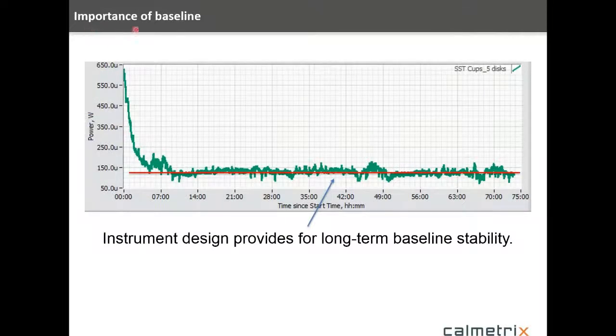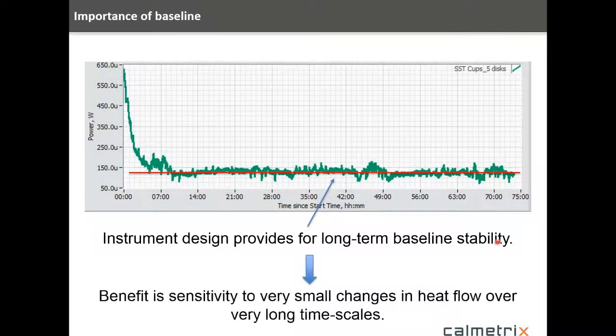Like other analytical instruments, baseline is very important. The isothermal calorimeter is designed for very long-term baseline stability, and that's very important. It basically provides us the sensitivity to look at very small changes in heat flow over very long time scales. So, of course, there's two aspects of sensitivity. The raw baseline noise is one issue, but just as importantly is the long-term baseline stability, because these reactions that we're looking at are very small changes in the baseline, and so a flat baseline is important to have the sensitivity that we need for these small changes over long time scales.